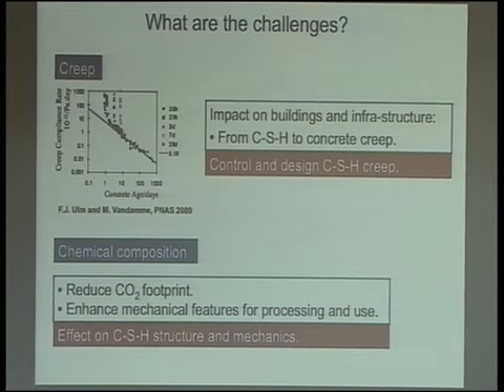And okay, just to have an idea of what the other implications are apart from the strength, for example, one thing is that concrete actually creeps. Of course, it's a creep that is very, very small with respect to polymers or any other system that Susan was talking about. So here, these are experiments done on concrete actually, and this is the creep compliance rate. Okay, so it's very small, but the point is that this is non-zero, and when you think that you want to use the material for a few decades and you want to build a very large-scale structure, then these are effects that you care about. And in fact, another interesting thing is that it's been proven by a set of experiments that, to some extent, this creep is probably associated to the aging of the nanoscale gel over time. And so that's another reason why you would really like to understand how the gel forms.